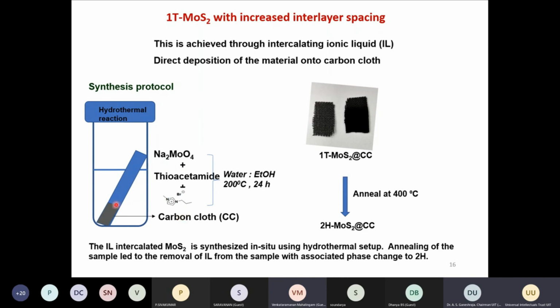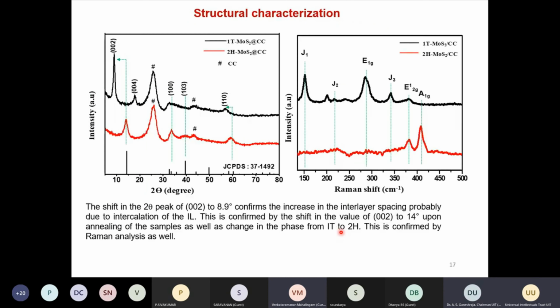So we thought, if we are able to prepare this directly on the carbon cloth. What we do is put the carbon cloth in during the reaction, so there is an in situ growth of this MoS2. You can clearly see that this is the carbon cloth. After the reaction, you see the black precipitate or product that is deposited on the substrate. To understand whether it is 1T or 2H, I'll come to the characterization, which is again a tricky part. What we do is anneal them to get the 2H phase. When we anneal at higher temperature, it is converted into MoS2 in the 2H phase. These two are on the carbon cloth. I will compare the results with the non-directly grown material, which is deposited on the carbon cloth, for comparison, to see how efficient it would be if we directly grow them on the surface.